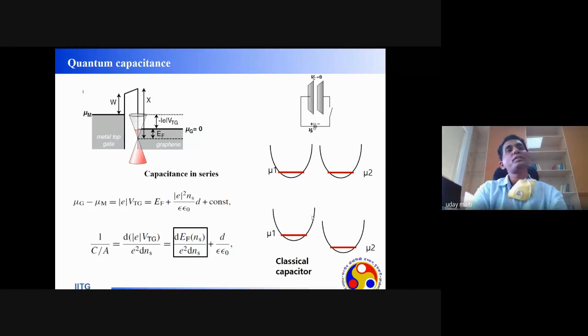And there is also a unique feature related to the low density of states near this Dirac point. If you make a capacitor, where one side of the capacitor is a metal and the other side is graphene, the capacitance is not determined only by epsilon 0 A by D. You know that for a parallel plate capacitor, the capacitance epsilon 0 A by D is inversely proportional to the distance and proportional to the plate area and the dielectric constant in between. But in this case, there is an additional term, shown here within a bracket. This additional term appears due to the finite, very low density of states near the Dirac point. And to give you an analogy for why this is happening,